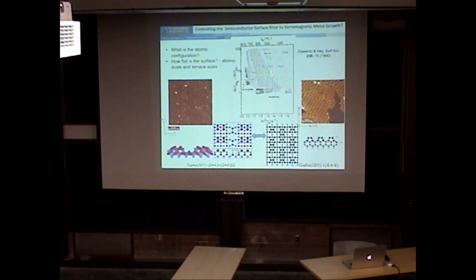So for example, the typical one, we call it a 2x4 or c2x8. This is what you typically have when you're growing in MBE, the surface is terminated by 2 arsenic dimers on the top surface, another arsenic dimer in the third layer down. This is sort of a typical surface. If you cool it down under arsenic, you get this c4x4 surface, which is a complete monolayer of arsenic and 3/4 of a monolayer of arsenic dimers on top. Now, if I'm going to grow my iron on top, which surface do I want to use? Do I want to specifically go for any of these reconstructions, or will anything work?